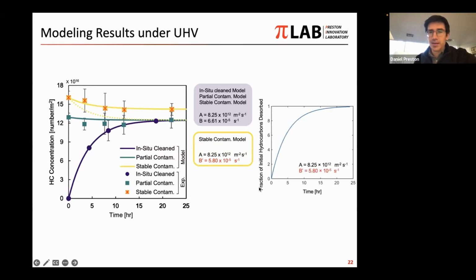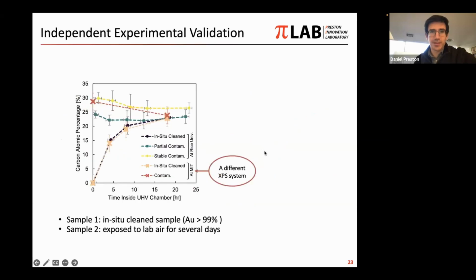up here. What we probably expect happening is that we have a transition from some initial hydrocarbons on the surface that have been stuck on there from the air environment, and then later some hydrocarbons that have been transferred onto the surface from inside the XPS chamber environment. And so these might be different species. And it could be the case that in a conservative situation, we're actually left with mostly the contaminants that are initially from outside of the chamber. And so we sort of bounded this prediction, but we found that all of the data points lie within the shaded region. So we were pretty excited by the ability to use this model to describe the experimental results.